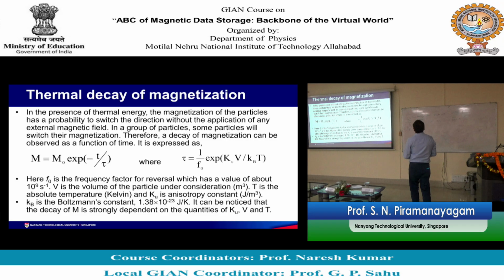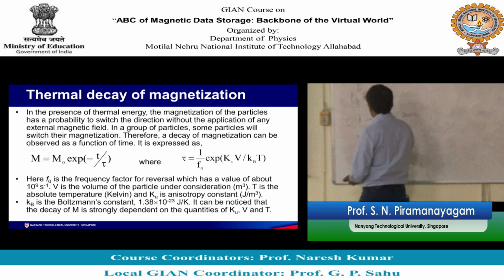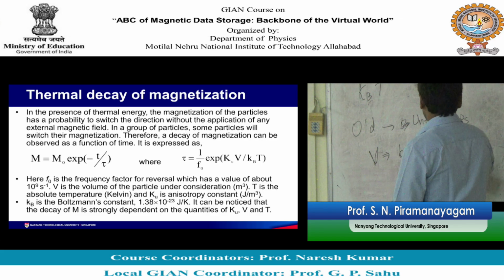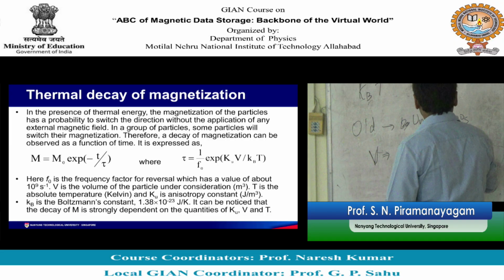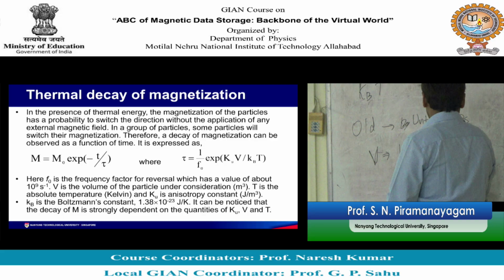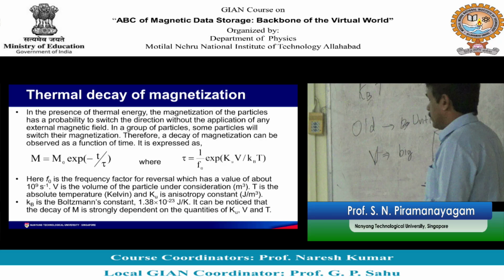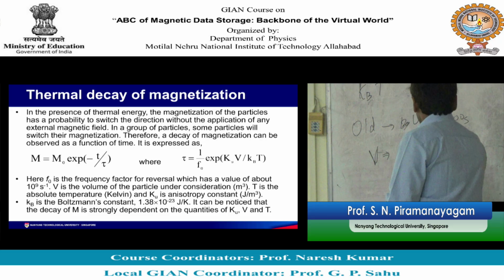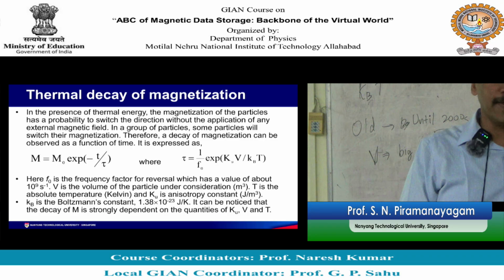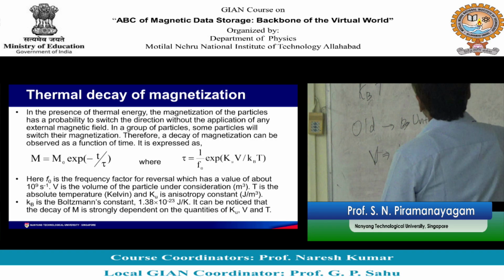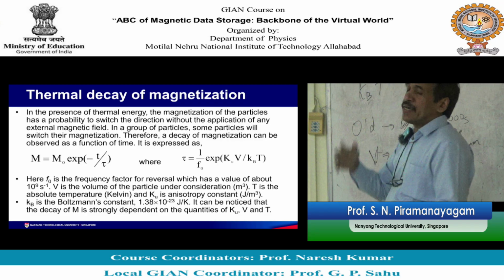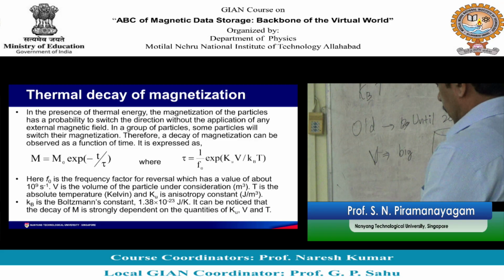I told you that in the old technologies, until the 2000s, the volume was very big. Let me give you some number. You have a grain diameter of maybe more than 15 nanometer, and height around 20 nanometer. When you have such a large volume, you multiply by KU, you will have a very large number for KUV. That number is very large compared to KBT.